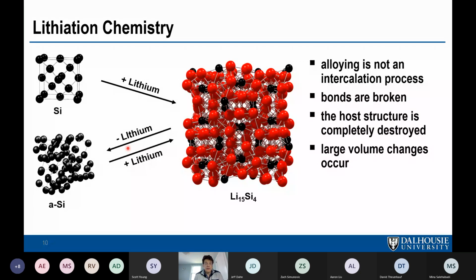When you take lithium out of this structure at room temperature, the atoms don't have the thermal energy to reorganize to the diamond structure, and so you form amorphous silicon. And the volume change represented on this slide is about right. You get about a 300% volume expansion during lithiation, and during delithiation, it contracts down again, but amorphous silicon has a slightly higher volume than crystalline silicon. So you get these massive volume changes during lithiation and delithiation.